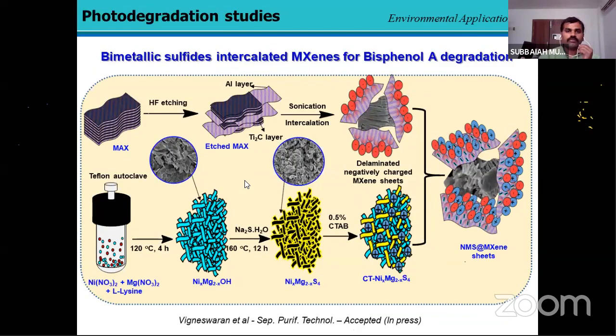Then when I was in South Korea, one of my juniors, Vigneshwaran, came to South Korea for his internship program. We started some bimetal sulfides, which are also 2D materials, intercalated on the MXene material for bisphenol degradation, and we successfully got results. We synthesized nickel-magnesium layered double hydroxide, which was further treated with a sulfur moiety to get the sulfur form, which is more beneficial.